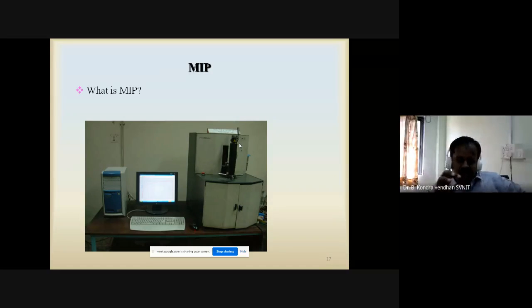Then the same sample is transferred to the high pressure station, which is on the top side, the black one. There we keep the sample and apply pressure from 20 to 60,000 psi. There also we get one more cumulative intruded volume versus pressure curve. Finally we merge both curves together using the software and get the complete cumulative intruded volume versus pressure curve. So we can apply pressure up to 60,000 psi.